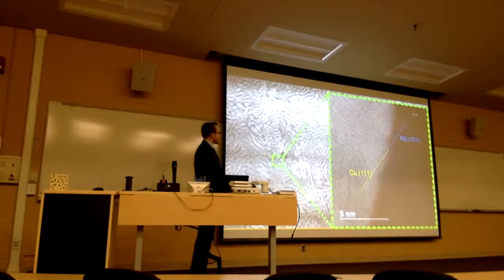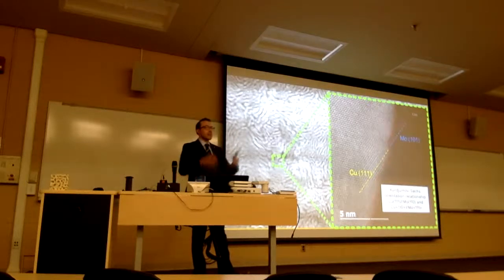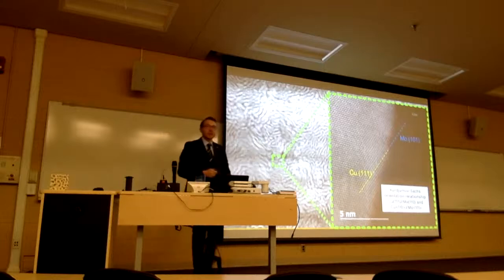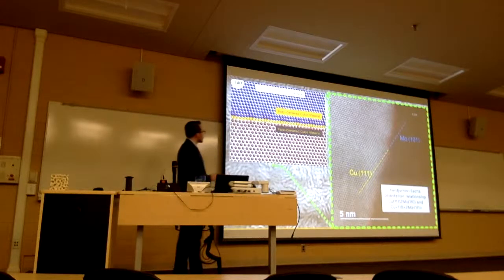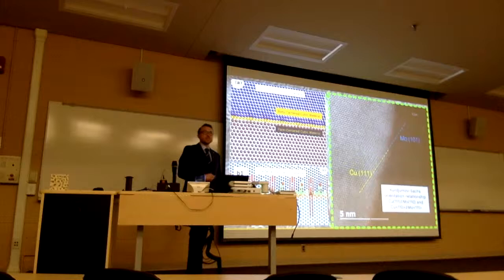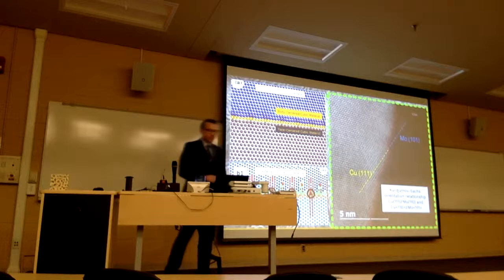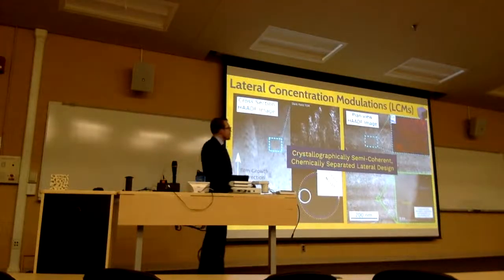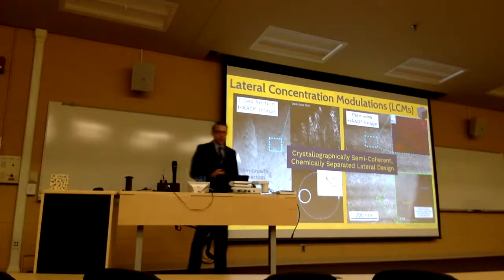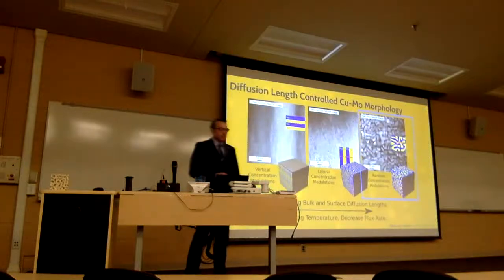TEM. If we look more closely at the interface between the BCC moly and FCC copper, you can actually see that this forms a semi-coherent interface between the two crystals, and it has a Kurdjumov-Sachs orientation relationship. An orientation relationship describes how two crystals are aligned with one another. In fact, it describes a set of parallel planes and parallel directions. And here's what that looks like schematically, where we've matched up body-centered and face-centered cubic material at the interface. And what's really interesting about this structure is that we have misfit dislocations that literally interface and actually provide for the mechanical performance, or describe some of the mechanical performance we see in this material. You can see those misfit dislocations described here. And so what we have in summary at this temperature and deposition condition is a crystallographically semi-coherent, chemically separated lateral design.